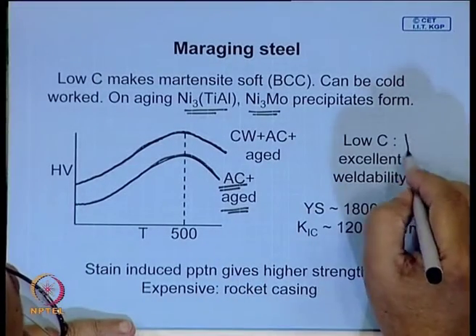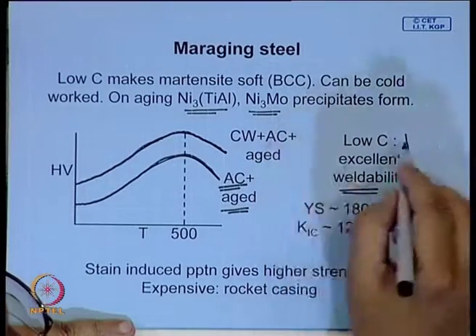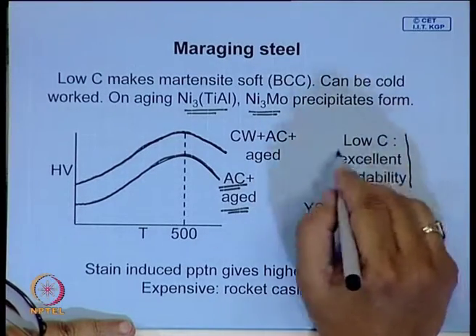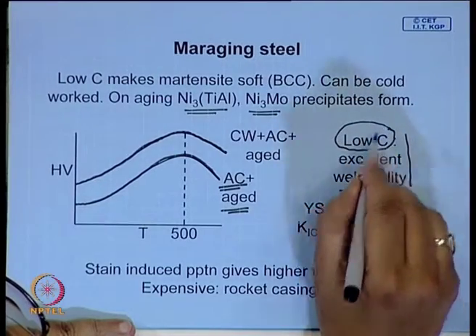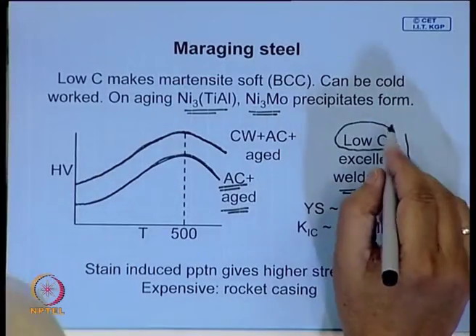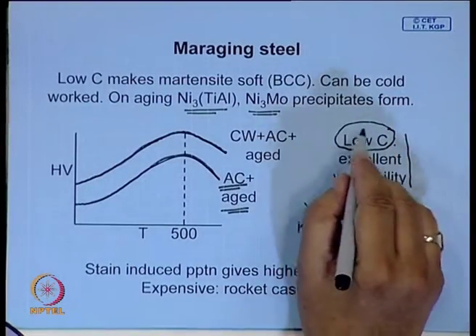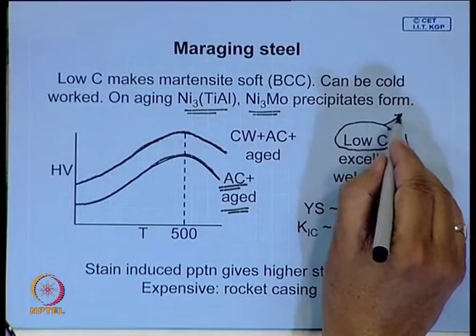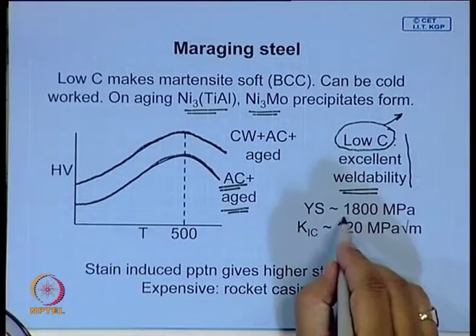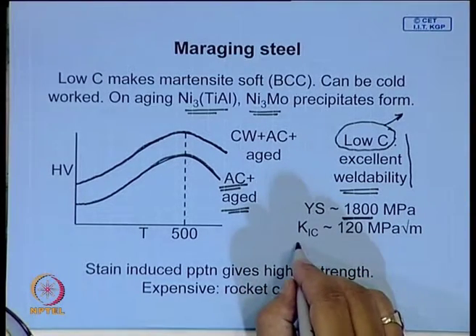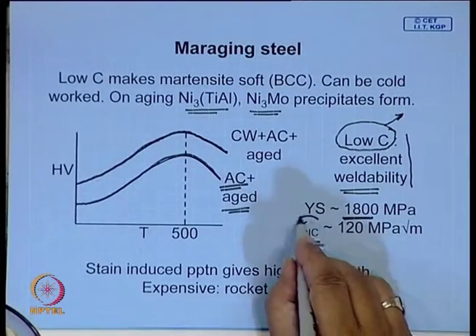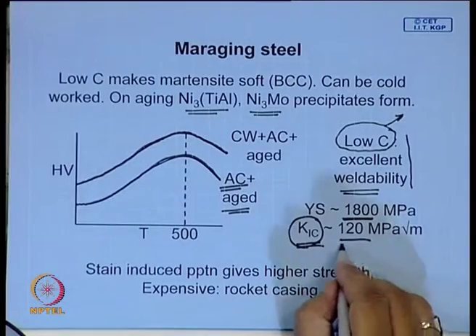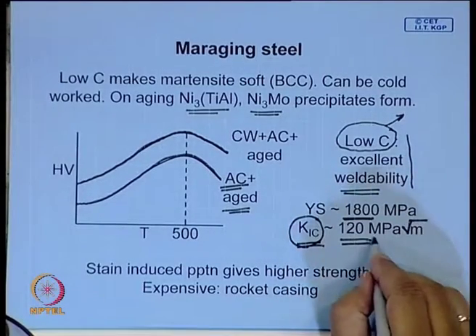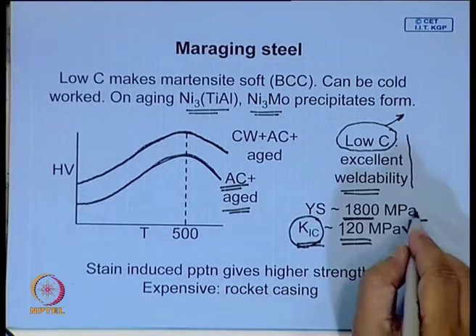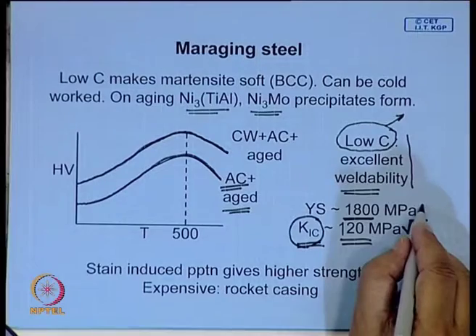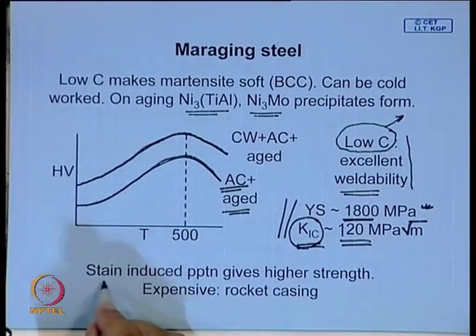And because of low carbon content, they have excellent weldability. We will see later that carbon is the main alloy element which is detrimental, which makes the steel difficult to weld. So, for good weldable quality steel, always an attempt is made to bring down the carbon content, and here the strength is extremely high. It also has very high fracture toughness. We did talk about K1C, which is a measure of fracture toughness. So, such a high level of fracture toughness, 120 MPa root meter, at 1800 MPa strength is unheard of. So, this is a very special grade of steel.